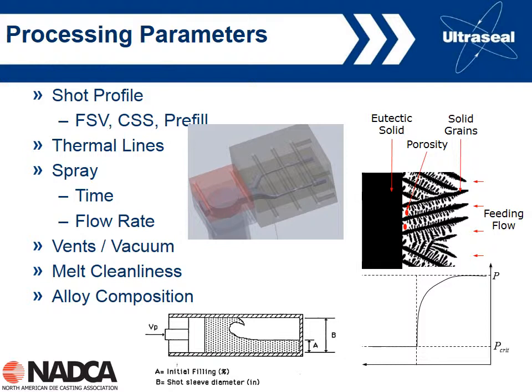We had talked a little bit about this in the first webinar, where we talked about the effect of alloy composition on porosity formation in terms of the size and distribution. We talked about the effect of the width of this mushy zone. So on the left here we've got the solid. On the right here we've got the liquid. We have this mushy zone, which is partially solid, partially liquid. To be successful, we've got to feed the liquid past these dendrites to get down to the base here, which is where the solidification shrinkage is really going to be forming.